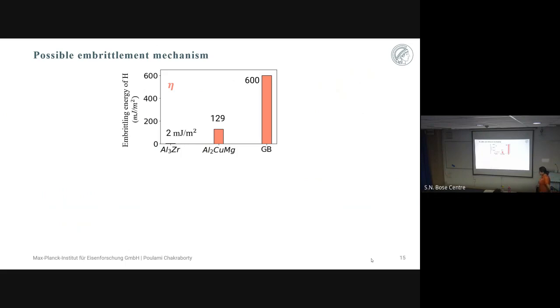So throughout I have discussed the importance of the factor eta, which gives us the embrittling energy, the quantity that tells us whether the system will be driven to the free surface. The larger the eta is, the larger is the probability that the system will be driven to fracture, which can be seen highest for grain boundary and lowest for aluminium zirconium. And this complies with the experimental results as well. This implies that hydrogen is much more detrimental at grain boundaries than when it is trapped in these intermetallic phases, because in that case it gets trapped in those sites, but it doesn't drive the system to a free surface.